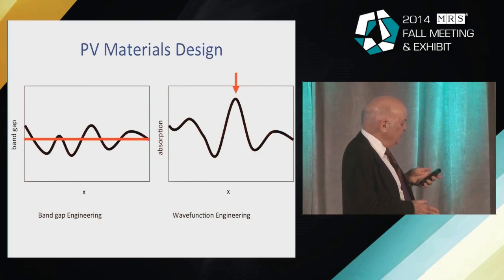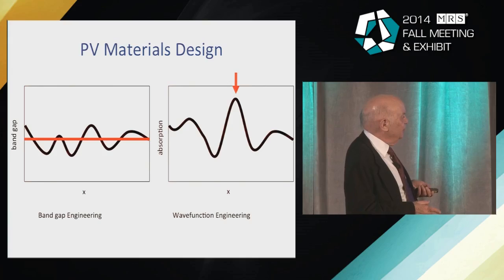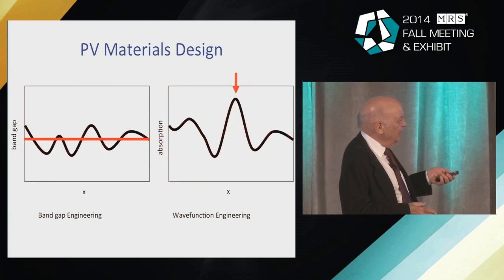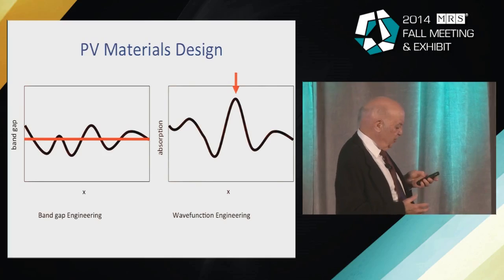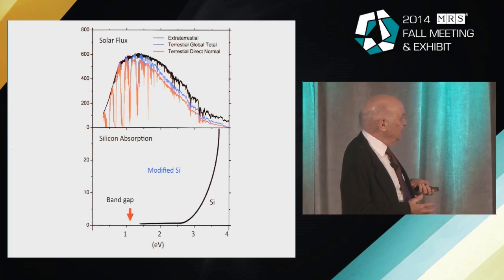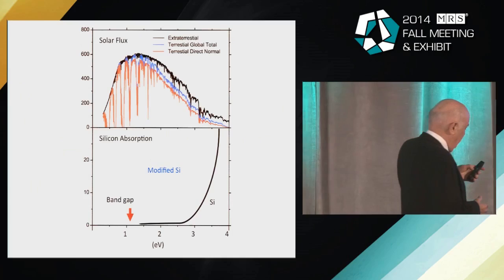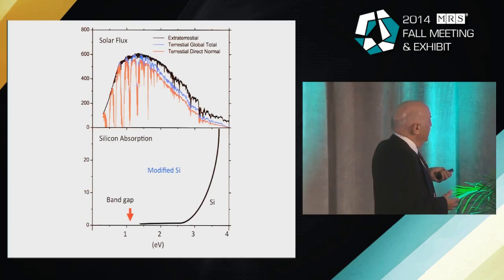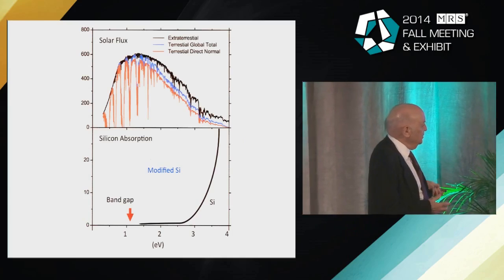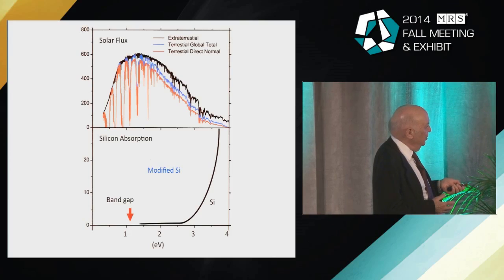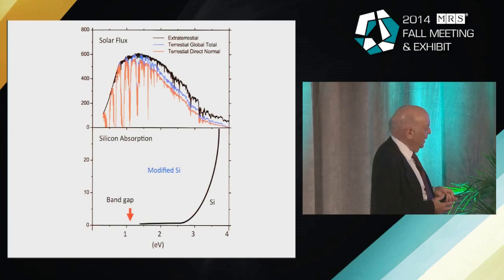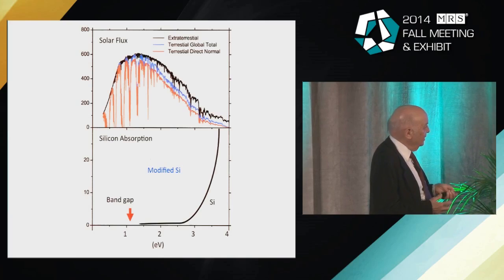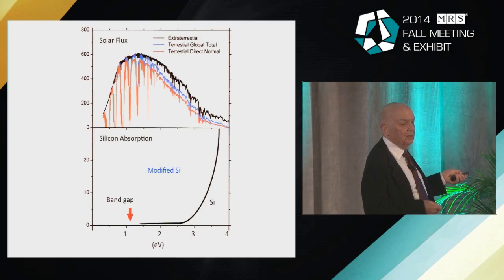So what you want is to get the best absorption coefficient as a function of x. And x here is really these high pressure structures. So this is just to whet your appetite about this area. Here's the solar spectrum, as a function of energy. And notice the ordinary diamond-structured silicon band gap is here. And the absorption is very flat in the region where the sun peaks.